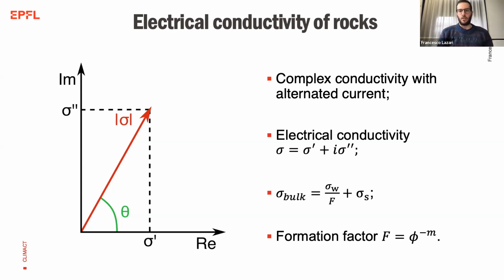When we measure electrical conductivity with alternating current, it is a complex number. We can represent it as a vector on the real and imaginary plane, and we can describe it with its modulus, the modulus of sigma, which is the conductivity, and its phase. In a saturated rock, so a sample that is composed of minerals and water within the minerals, the bulk conductivity is given by the fluid conductivity, sigma W, divided by the formation factor, plus the surface conductivity of the minerals.